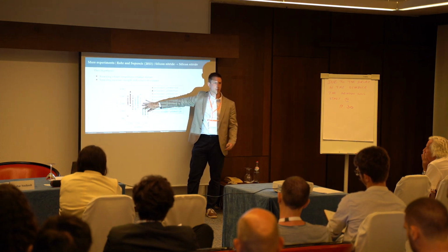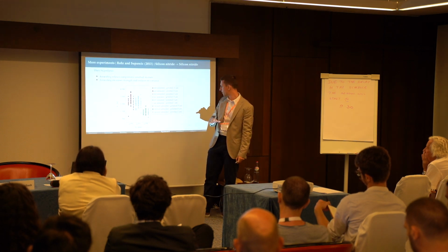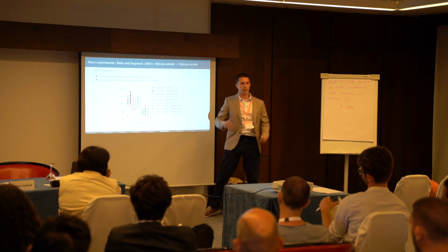When he annealed this middle set at 1000 degrees, again nothing. But then when he annealed that in vacuum at approximately, I guess, 1400 or 1600, suddenly the forces drop. So that should be an indicator of what's happening and what we are missing.